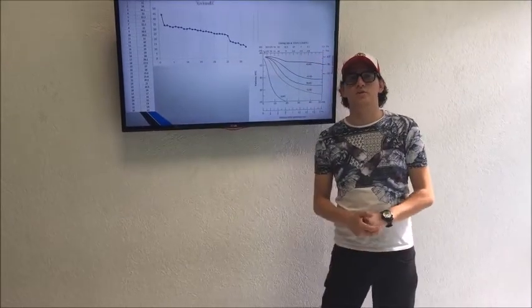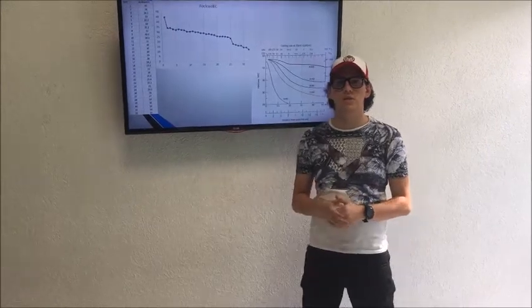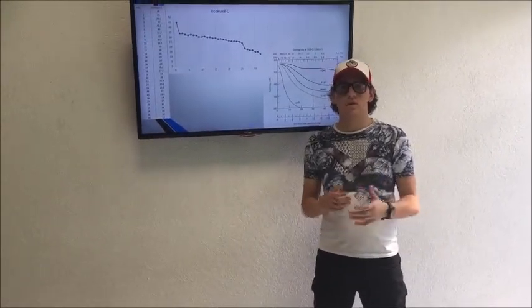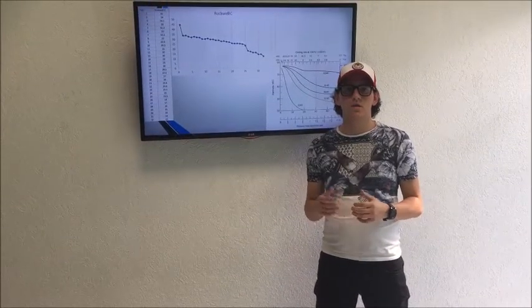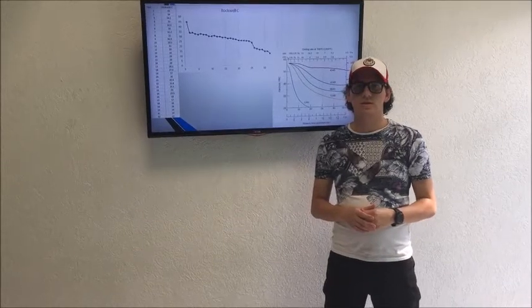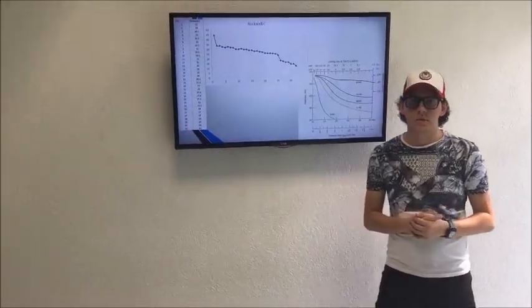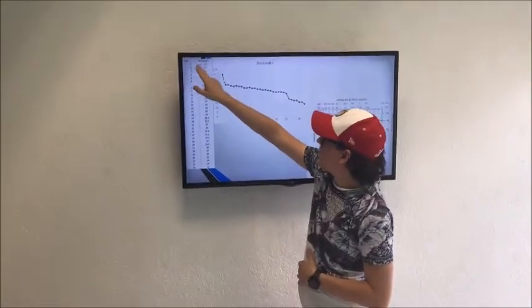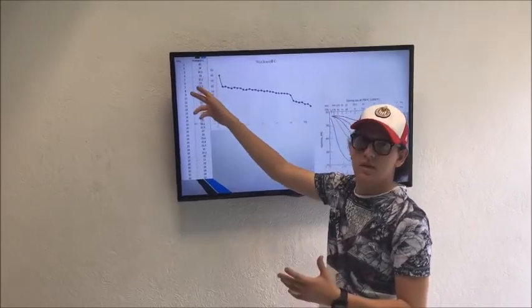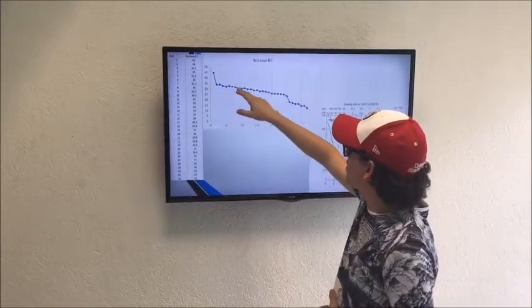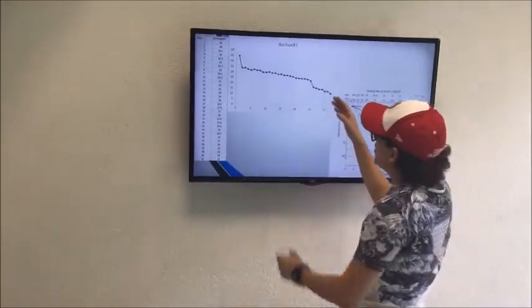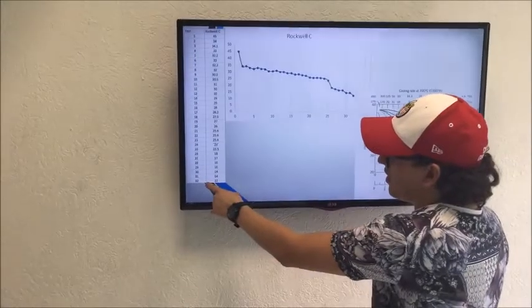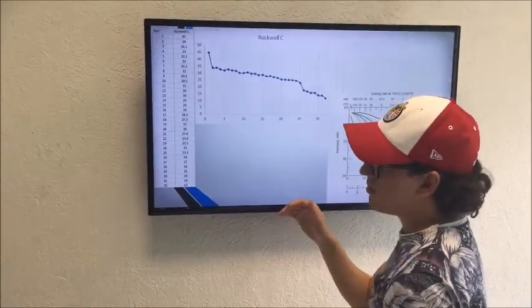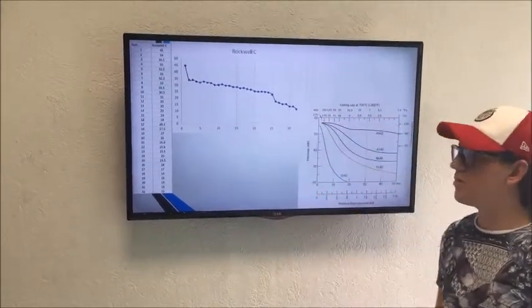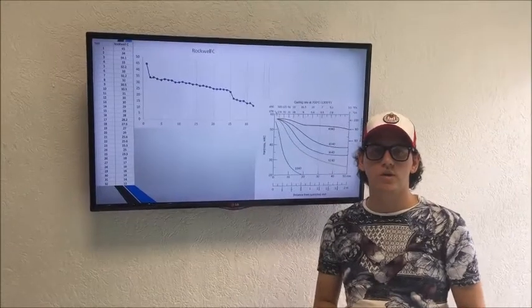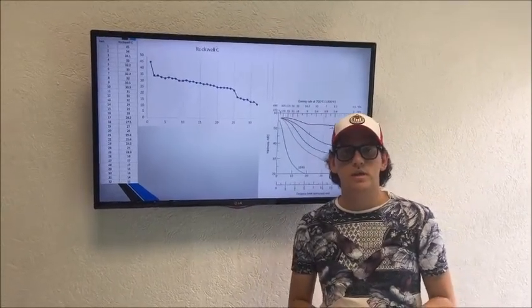The Jominy curve describes how the hardness decreases along the material because of the cooling rate. The material presents a higher Rockwell number at the beginning because it's cooled instantaneously when it touches the water. Here we can see our first test, that is 45, where is the martensitic reaction, and here we can see the curve decreasing because the material is cooled at a lower rate in the probe 32. The results that we obtained in the practice are similar to the results that we found on the internet.